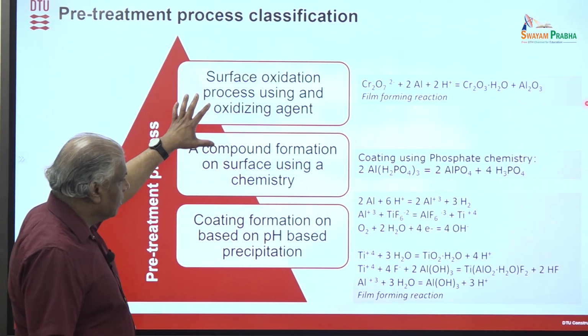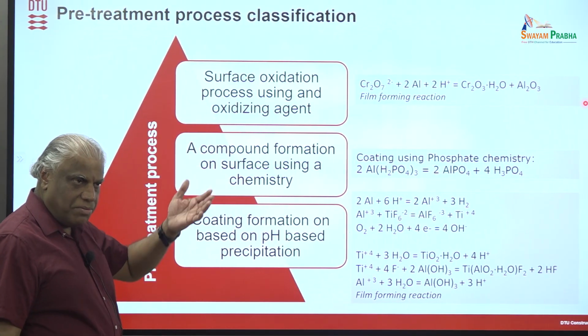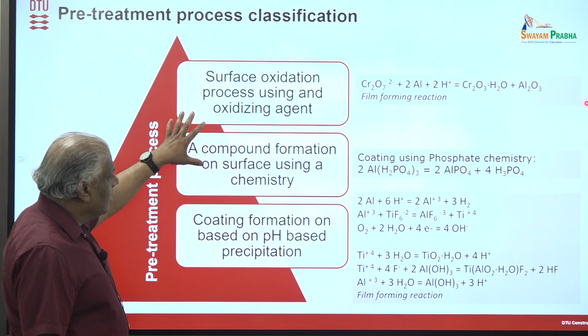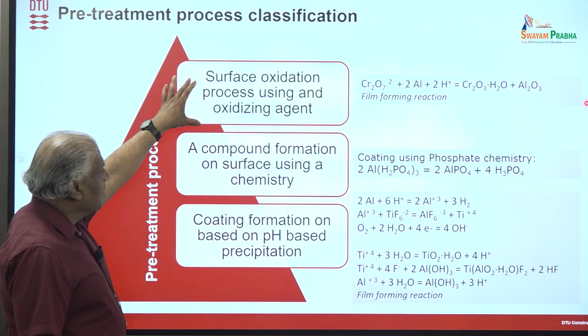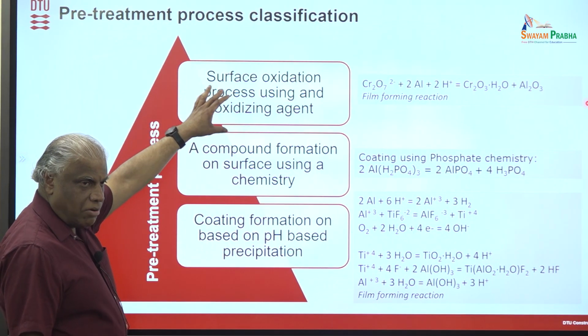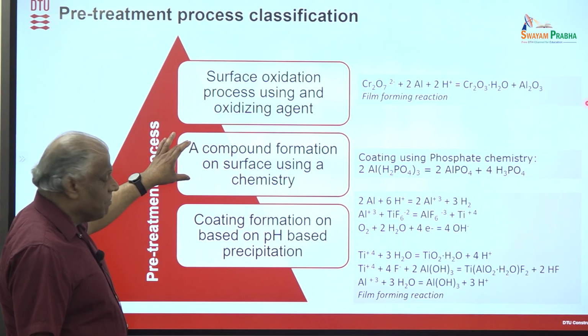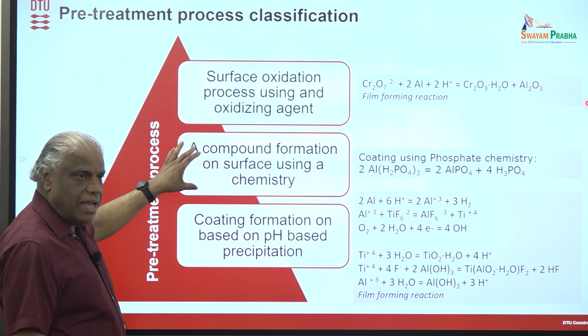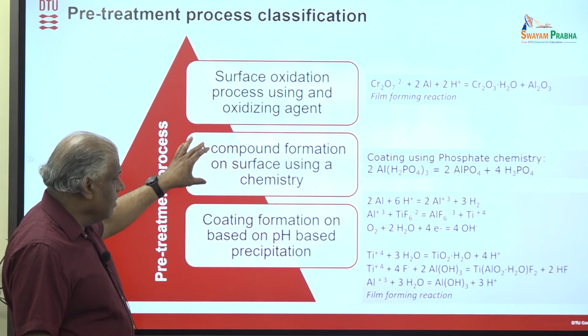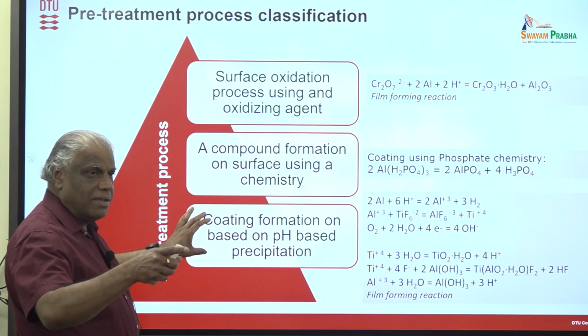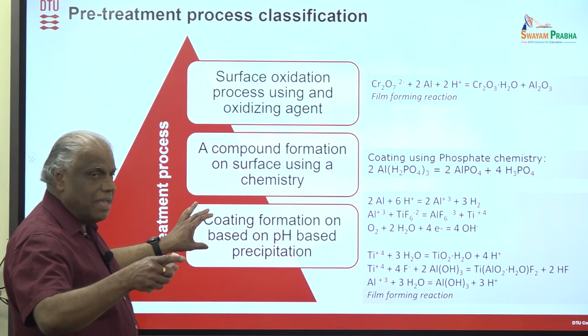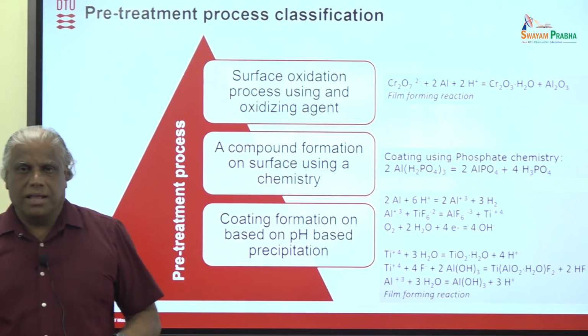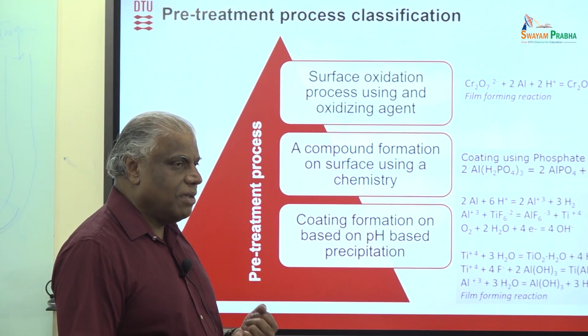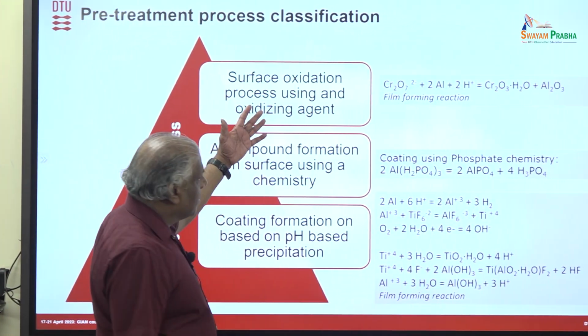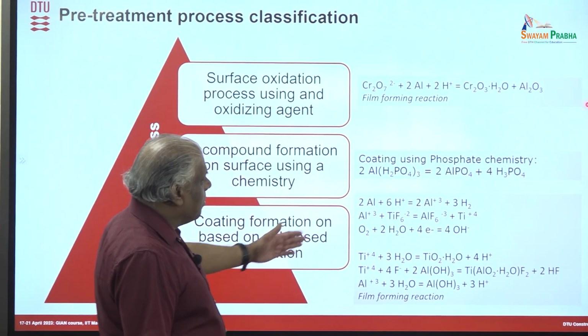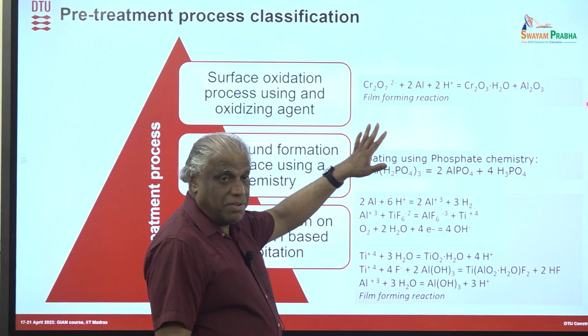So if you look at the conversion coating chemistry, from the green point of view, you can think that there are 3 conversion coating chemistries today. One is surface oxidation using an oxidizing agent like chromate. Another is compound formation on a surface using a chemistry, that means that something is directly attacking the surface and forming a compound. And the third one, which we saw earlier, is cathode inhibition, where we can make a pH-based precipitation on the cathode, and that way you can make a coating. So these are the 3 technologies which are going on, and that way you can think about the replacement as well. And when you think about all these, nothing is as good as chromium even today.